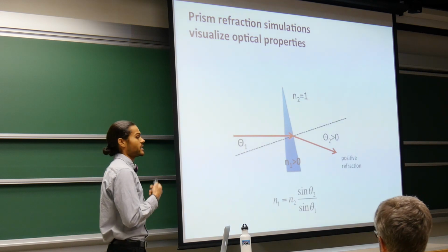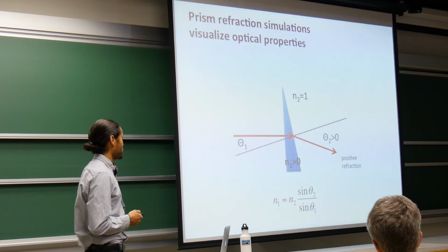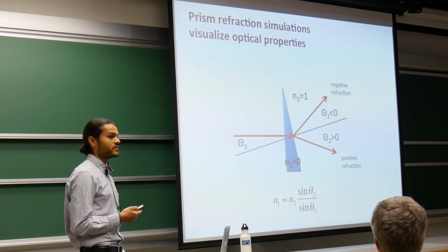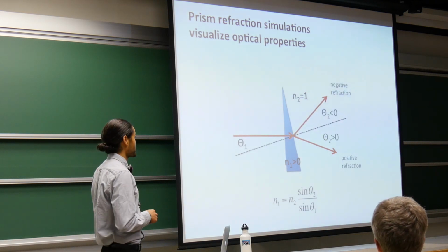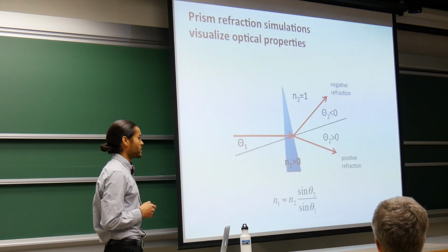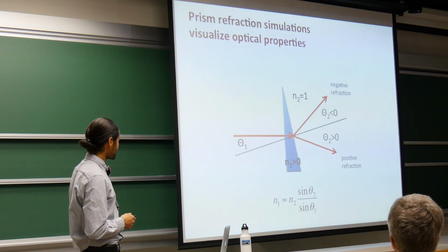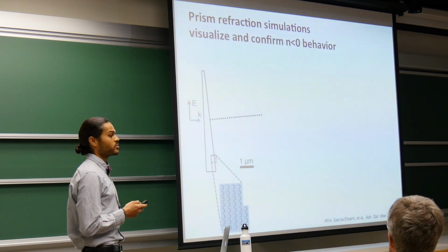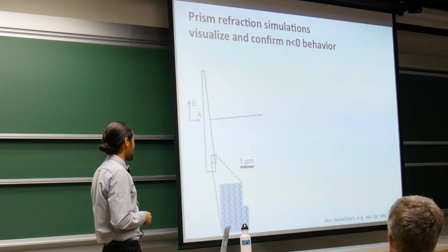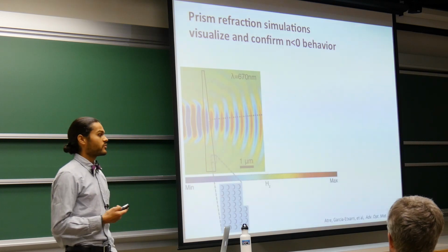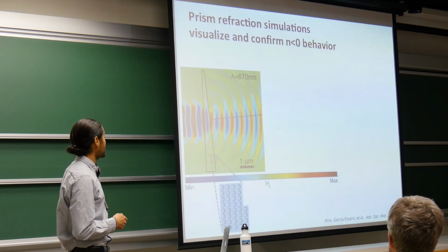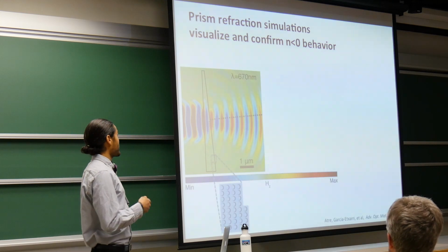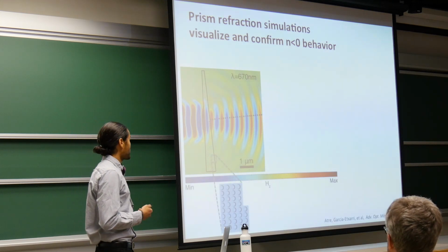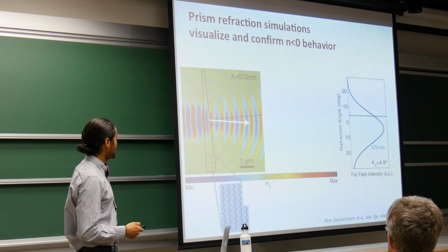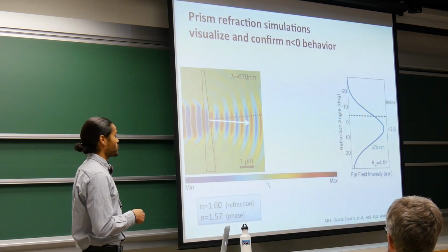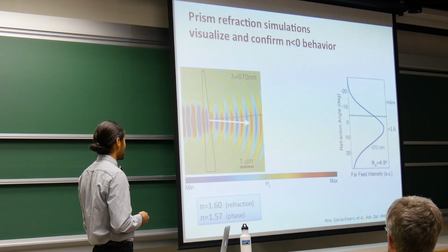So in this case, if light bends below the normal, that is positive refraction. And if light bends above the normal, that's characteristic of negative refraction. And if it travels along the normal, that's where the refractive index would be about 0. So here, we essentially make a prism, in theory again, with our crescents. And at a wavelength where we have previously calculated using that interferometric technique a positive index, we see that in fact the waves are bent below the normal, characteristic of a positive index of refraction. And if we actually use Snell's law to calculate that index, it corresponds quite well with our interferometric technique.